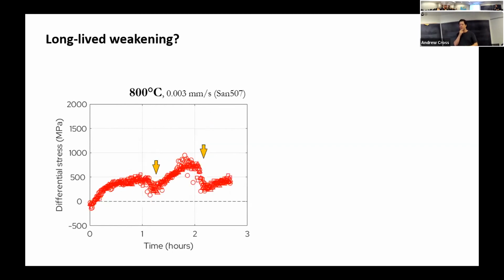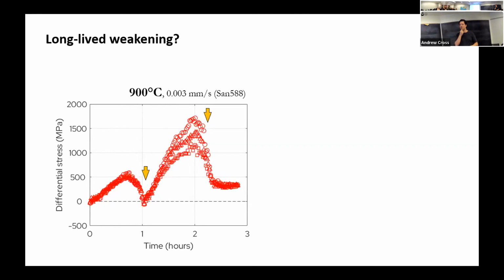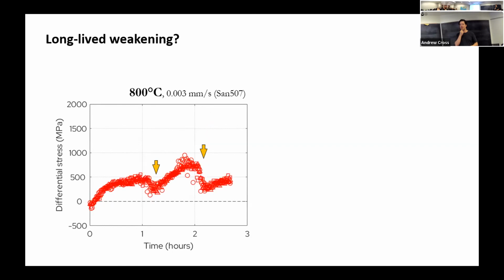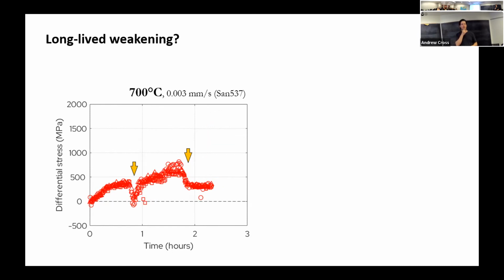So that's good. Once we go to 800 C, so we're going colder now, the sample gets weaker, coesite gets weaker. And as we go, so our steady state-ish stress here has gone from about just over a GPa down to 700, 750 MPa. As we go to 700, again, same rate, but lower temperature. Now our steady state stress is 500. This is quite weird. If we think normally about crystal materials, we expect them to get weaker as they get hotter, as they get softer. But in this case, we've got material that's getting weaker as it's getting colder.